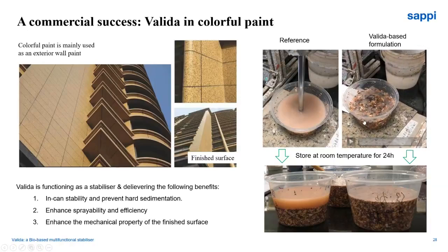sedimenting. And this, of course, is a massive improvement, because apart from better stabilization, it doesn't show any hard sedimentation issue. As you can see, after 24 hours, the reference formulation has all the stones sedimented, while the 3D network of Valida and the high surface area of Valida help in keeping the stones in suspension.